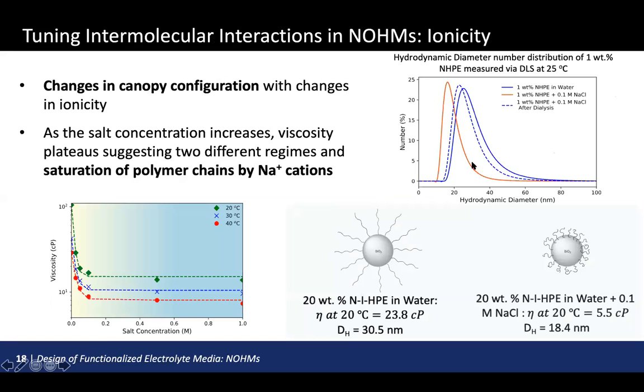So what you see here on the top right is the distribution of the size of NOHMs molecules in solution that we obtained from DLS. And we see that in the absence of salt, the blue curve here, the size of NOHMs particles is about 35 nanometers. However, when we add 0.1 molar sodium chloride, we see that this size actually decreases to about 18 nanometers. So we began to think that the polymer canopy of NOHMs is responsive to these changes in ionicity.